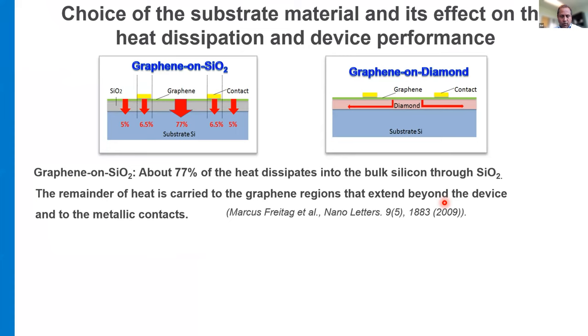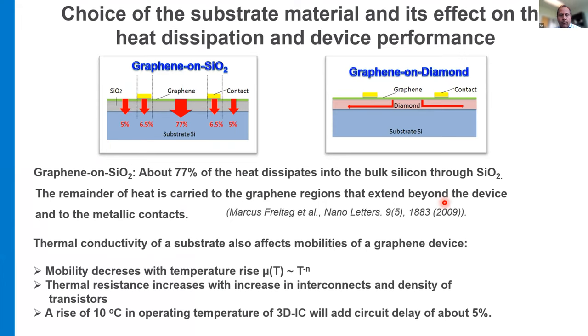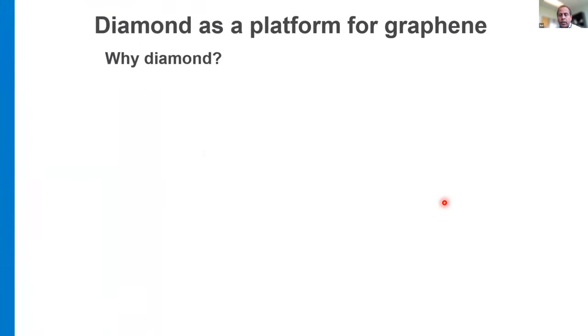There has been a lot of work done with integrating, of course, graphene-based devices on SiO2. But if you look at graphene on SiO2, about 77% of the heat dissipates into the bulk silicon through this SiO2, and the remainder of the heat is through these contacts. But if you look at the diamond, then you can get, of course, the benefit of the very high thermal conductivity of the diamond. And why the interface is so important is because the mobility decreases with the temperature rise. If you look at a rise of, let's say, 10 degrees centigrade in the operating temperature of a 3D integrated circuit, it will add about 5% of the delay. So it's very important to have very high thermal conductivity when you're building devices on a substrate.